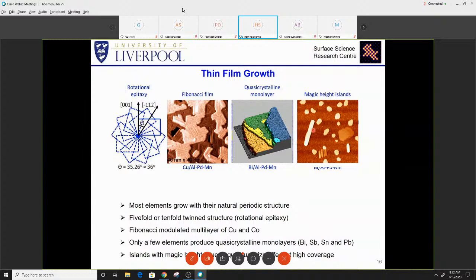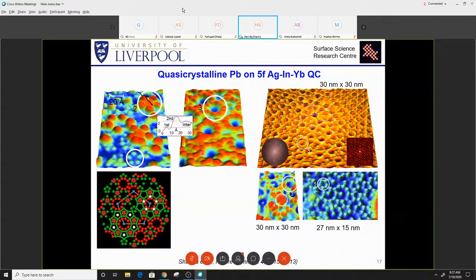In most cases, we saw quasi structure of one atomic layer, but in the rare case, we are the first to demonstrate that the quasi structure could be extended up to three atomic layers. Here's one example we published. Again, this is lead deposited on another quasicrystal. You can see this nice small pentagon. This is the pentagon of the first layer, and then the larger pentagon of the second layer. If you put more lead on that, the space will fill and you see complete patterns.